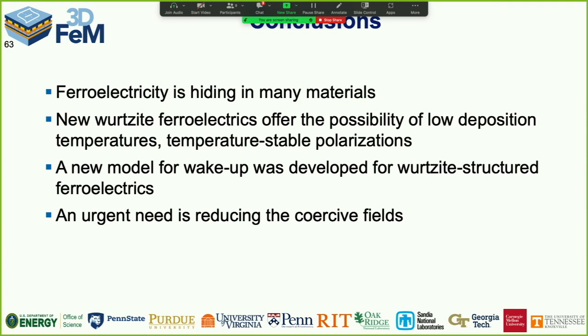And with that, I'll make my final conclusions. Ferroelectricity is hiding in lots of materials, so we can go find it. We can go choose materials where we want to turn ferroelectricity on and off. We think one way of doing this is by poising materials on the brink of a structural instability, making their susceptibilities big. The new wurtzite structured ferroelectrics offer this amazing ability to deposit relevant materials, which are not just fab friendly, but the fabs are like, I'm comfortable with this. This is fab comforting materials. At temperatures where they're not going to be upset about this, 400 C down, you've got the back end of the line to work with.